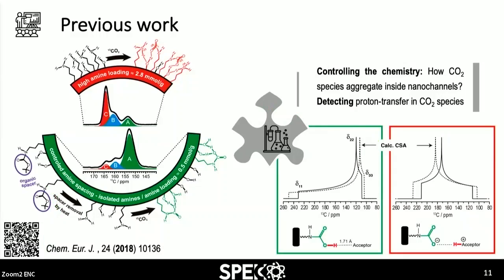synthesize, which is represented here, materials in which we have different distances between the amines. And for that, we have inserted a spacer. So basically, we force the amines to be separated, and we increase the amount of isolated amines, and vice versa. So we have different types of materials with different interamine distances between them, and this way we can correlate that. We know that the intensity of these chemisorbed species is nicely modulated by this amine coverage.